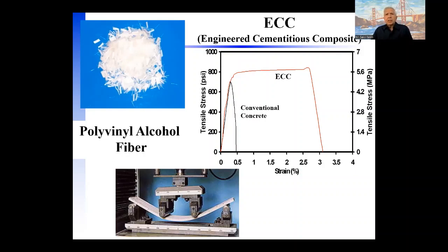capability, tensile strain hardening, and the ability to go to relatively high tensile strains, much more than what you get in conventional concrete. So what you see here is one of our test results. We saw tensile strain capacity of over 2.5%. The literature reports up to 5% that we have.